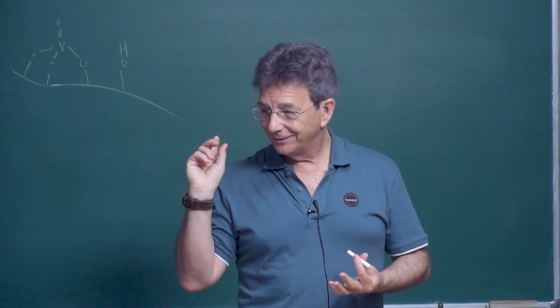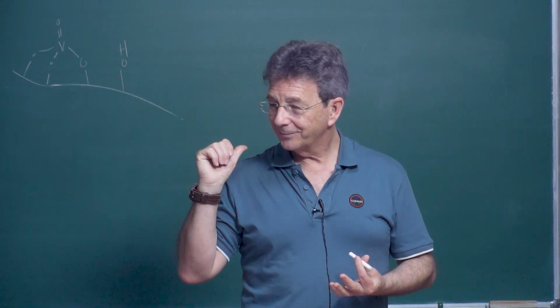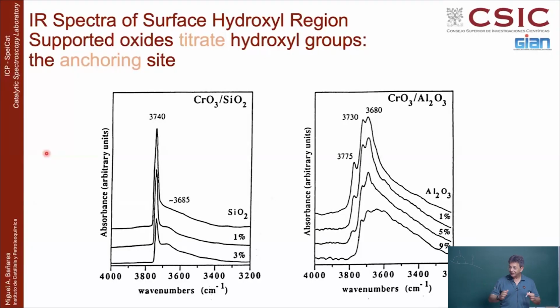You see that? So it will act as anchoring sites. Exactly, it's an anchoring site. That is the key word. So basically they will titrate them and they will react. So if you are looking at a catalyst like chromium oxide on silica, this is the infrared spectrum of bare silica. You have an intense hydroxyl group.